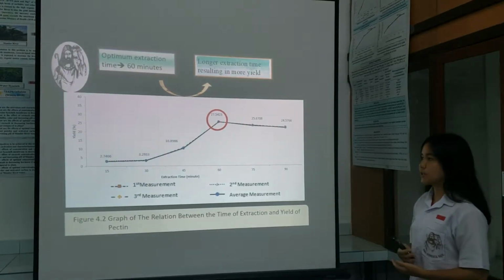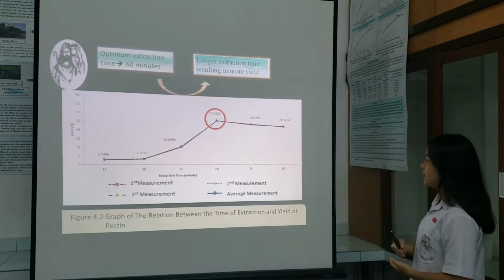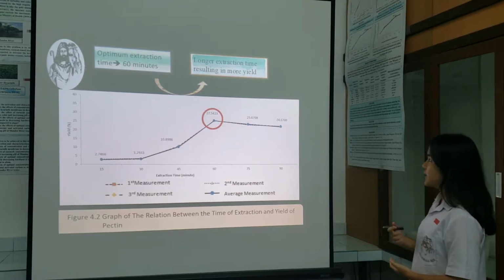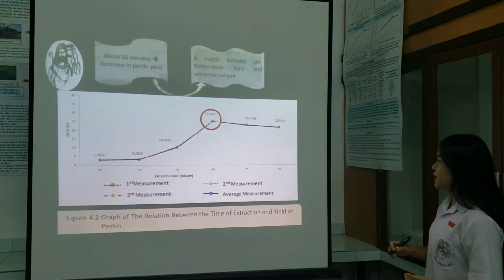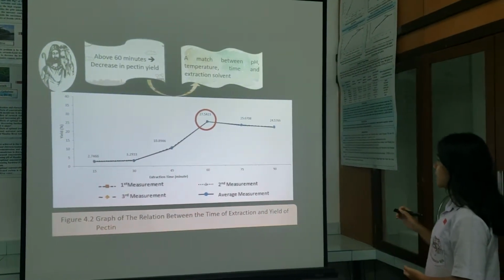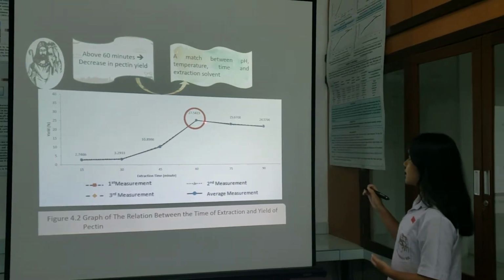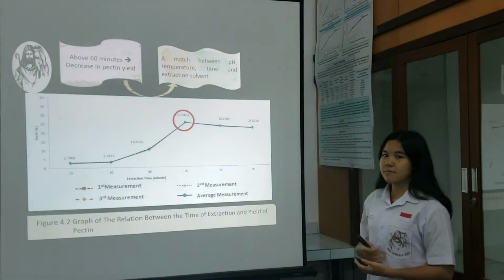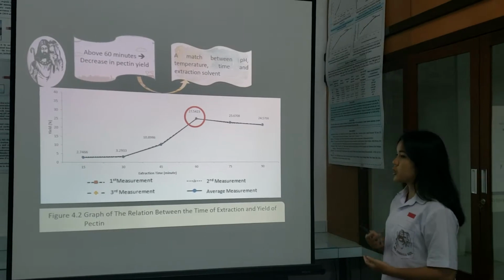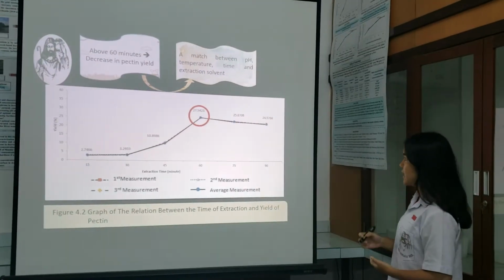This is because longer extraction time will cause a higher hydrolysis kinetics, resulting in more pectin. However, we can see that at an extraction time above 60 minutes, there is a decrease in pectin. This is because a match between pH, temperature, time, and extraction solvent is needed.